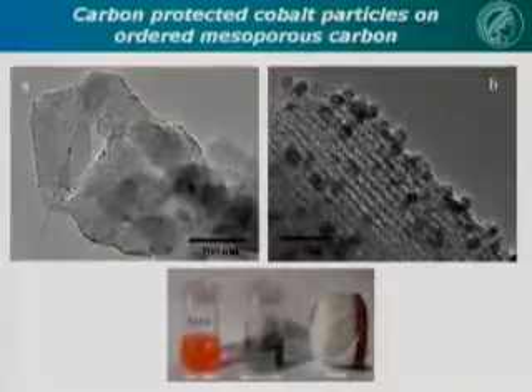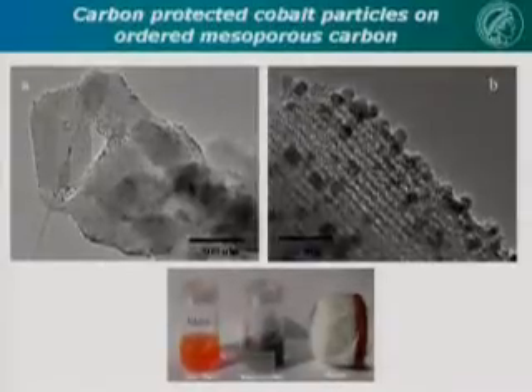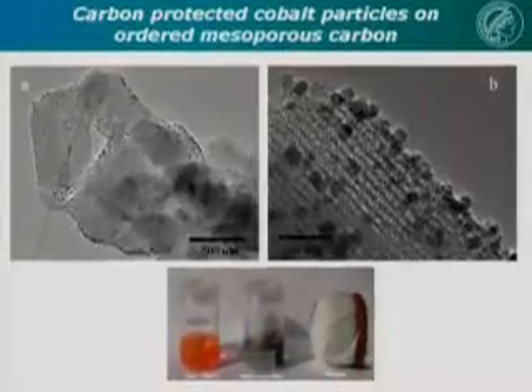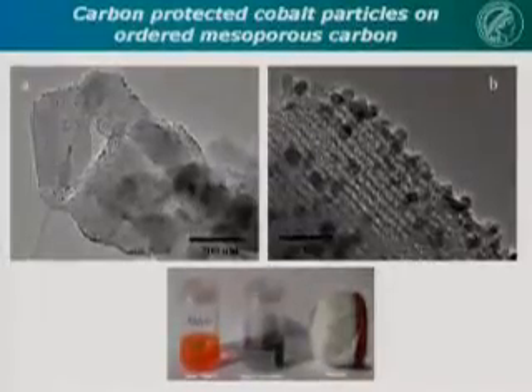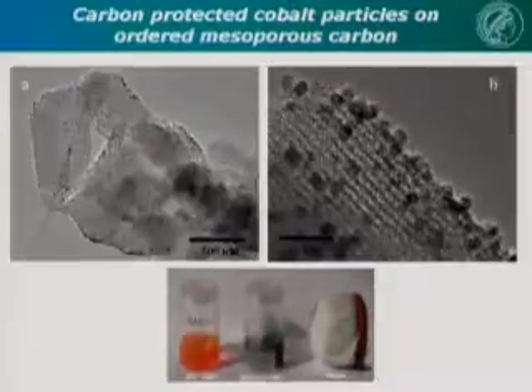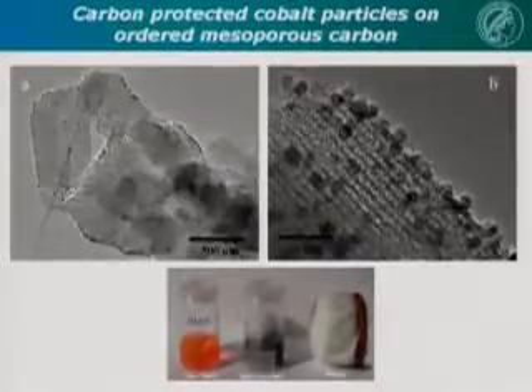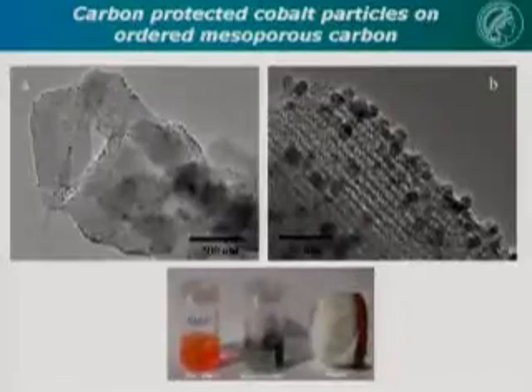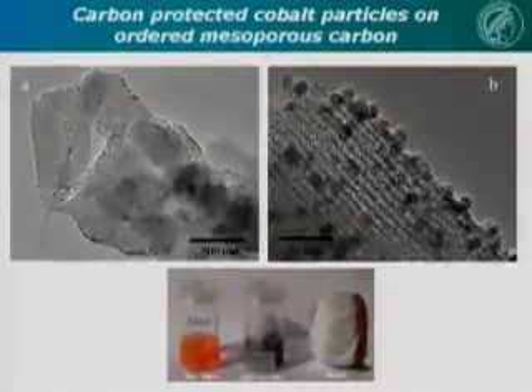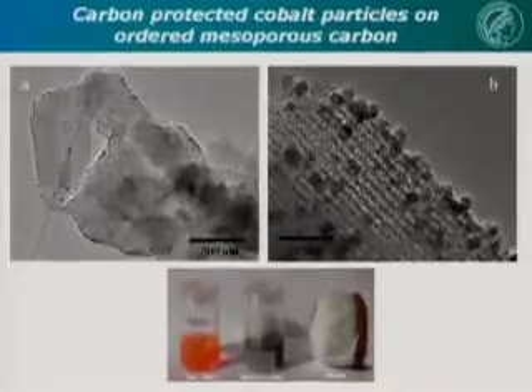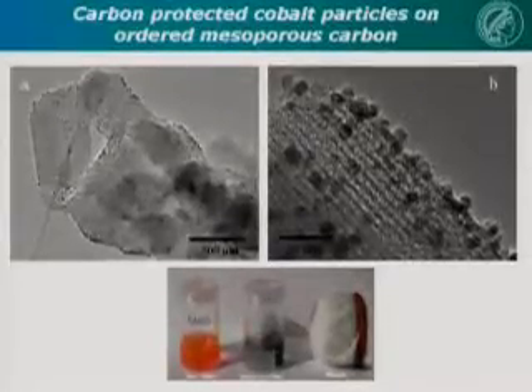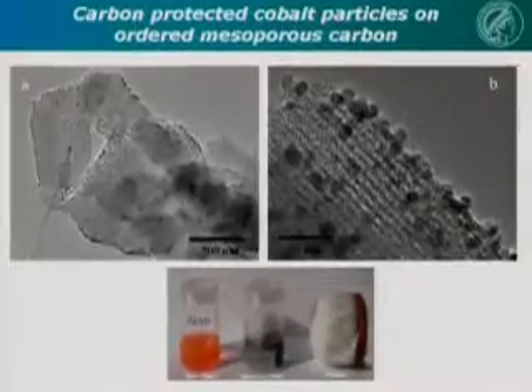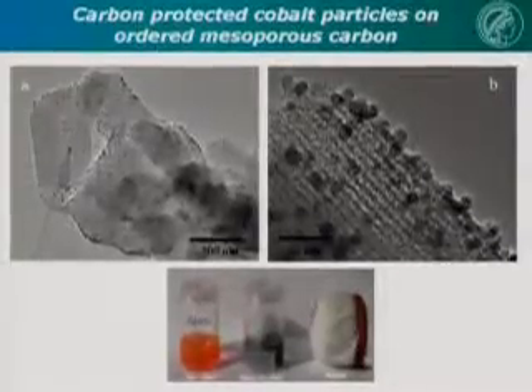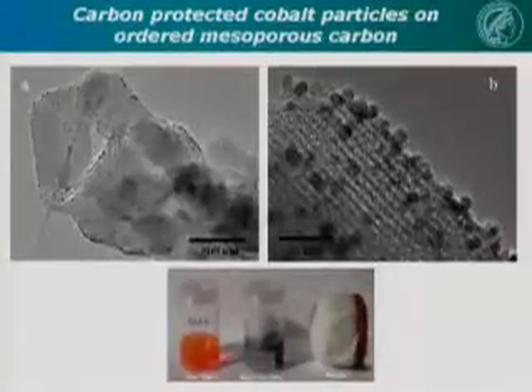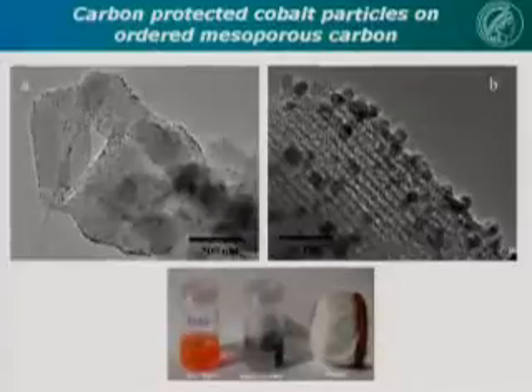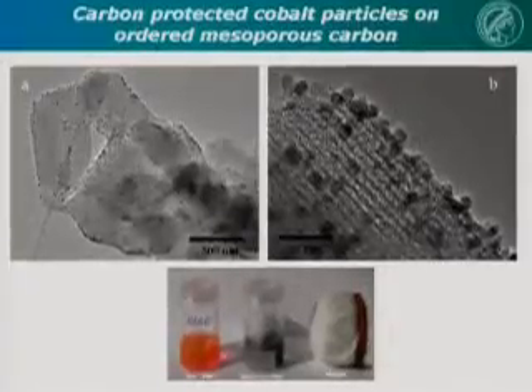We can use it to decolor dye solutions. And here you can see these are all 9 nanometer particles protected by a thin carbon shell, about 1 nanometer thick. But the protection is so good, you could leave that for half a year in semi-concentrated nitric acid, and the solution would remain colorless. So no cobalt leaching, because if the shell was not perfect, the cobalt was already leached during the silica leaching step. And you can see here, here is an empty shell, here is an empty shell. So about 20% of the shells are not perfect. From them, you leach out the cobalt, and in the rest of the shells, the cobalt stays even under very corrosive conditions.